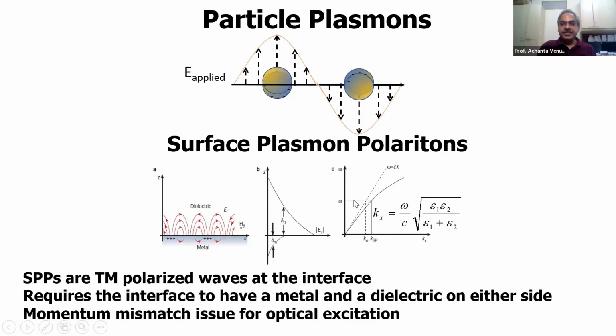So you have some issues with coupling shining light and directly exciting this plasmon mode, because of energy conservation. This is the light line, omega equals c k, and this is the plasmon mode dispersion curve. The omega of the photon and the omega of the plasmon should match for energy conservation, and at the same time the k of the photon and the k of the plasmon should also match, which doesn't happen because there is a mismatch here in the k values. So you cannot directly shine light on an unpatterned interface and excite these plasmons.